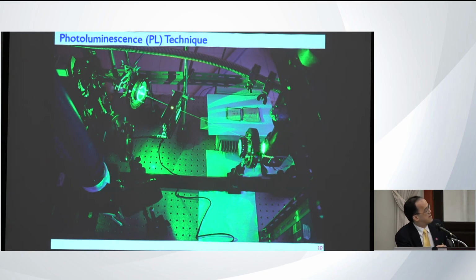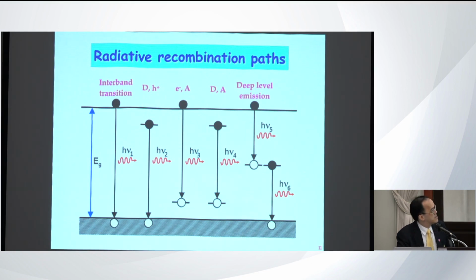The sample is here in the cryostat, where we can control the temperature from room temperature down to 10 Kelvin. Then the luminescence is emitted in front of the cryostat and collected by the lens to the detector. And I would like to mention all the radiative recombination paths that are possible when we do the PL measurement.